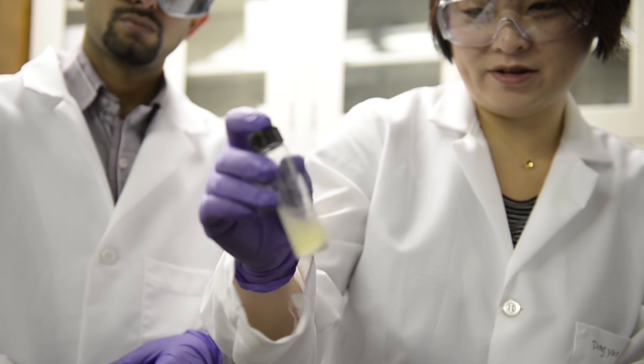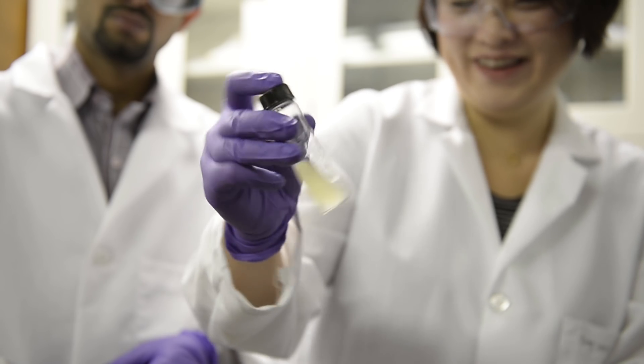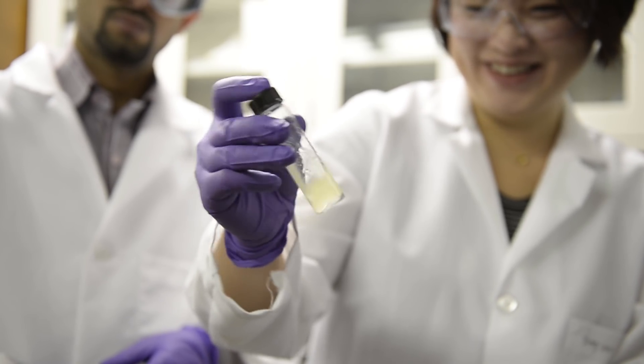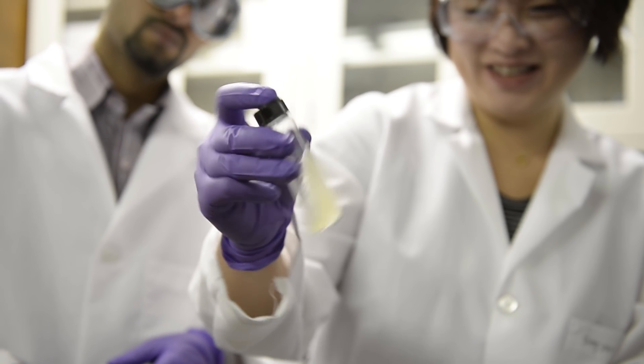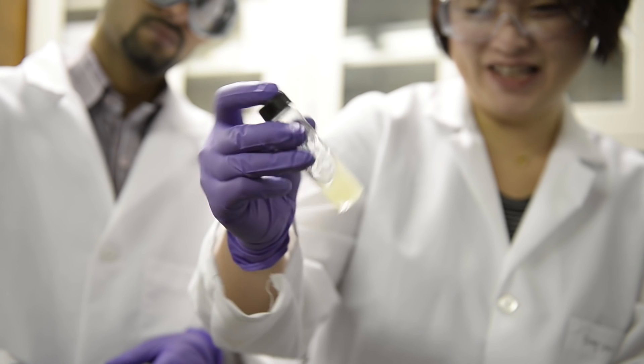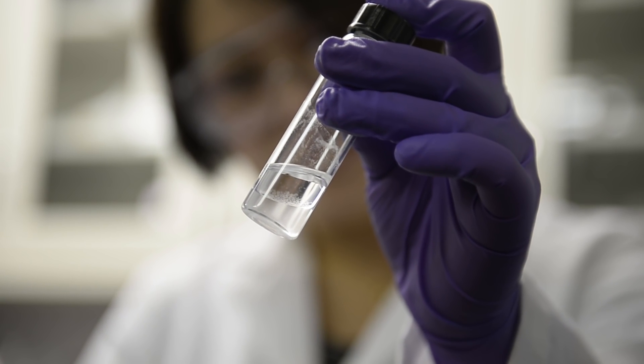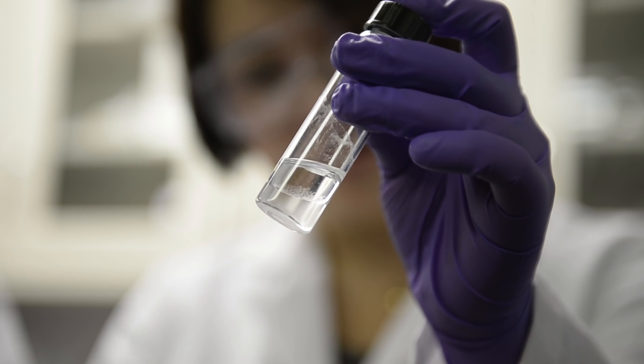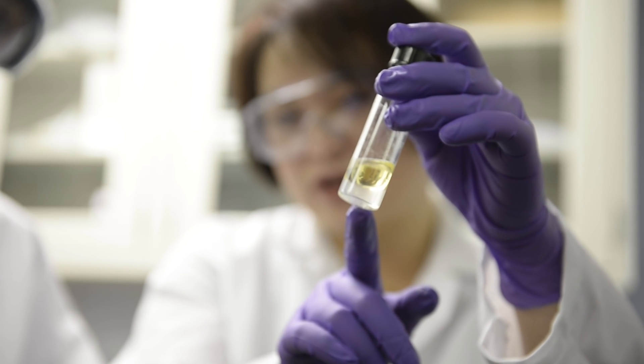During the hand-shaking process, emulsion happens between the water and the organic layers. They let the emulsion rest for a few hours to one day. Hexane is very fast — it can start to separate into two phases in three to four hours, or even one hour. The cooking oil takes longer, about one day to settle down into two layers, after which the emulsion phase separates back to organic and water phases again.